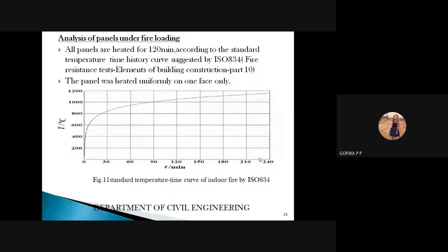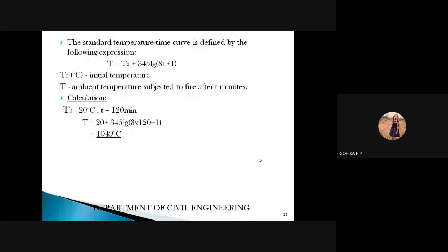This figure shows the standard temperature time curve of indoor fire by ISO 834. The standard temperature time curve is defined by the following expression, that is T equal to T0 plus 345 log(8t plus 1). T0 is initial temperature and T is ambient temperature subjected to fire after t minutes. Here initial temperature taken is 20 degrees Celsius and time is 120 minutes. So T equal to 1049 degrees Celsius.